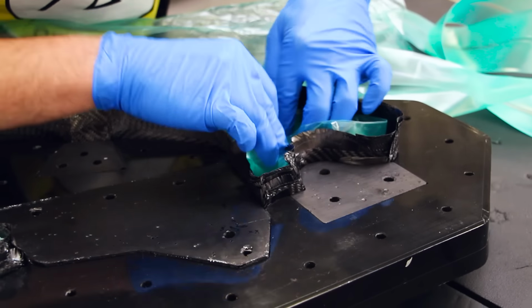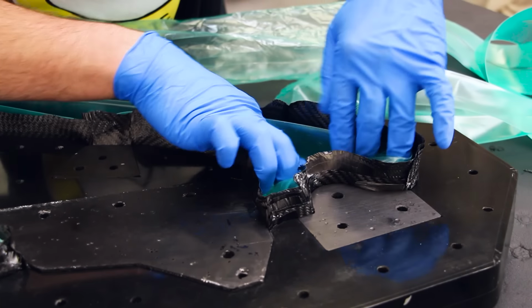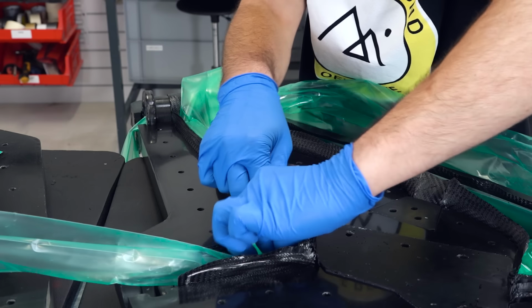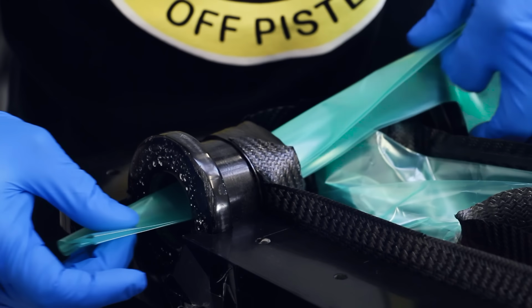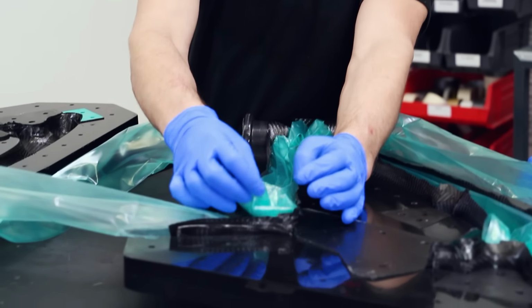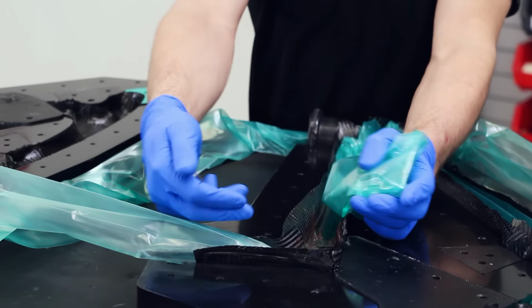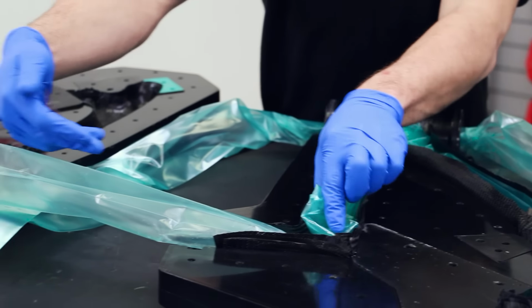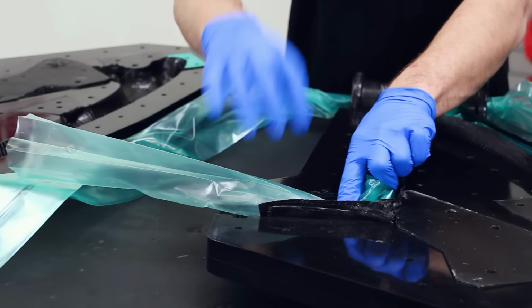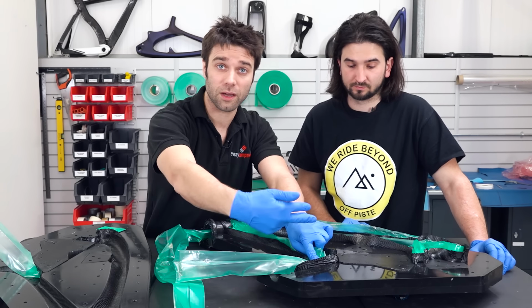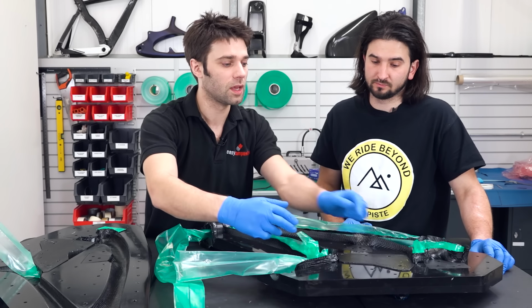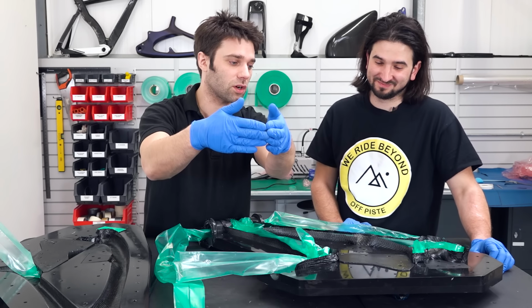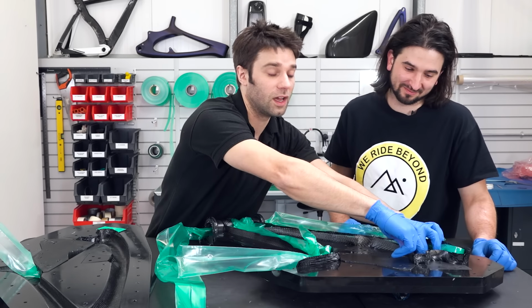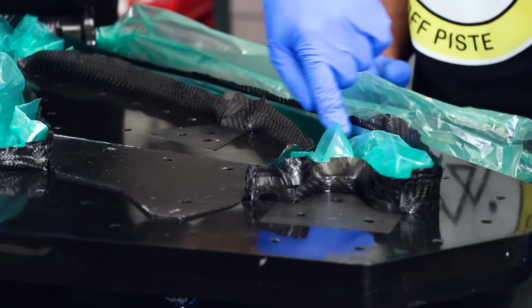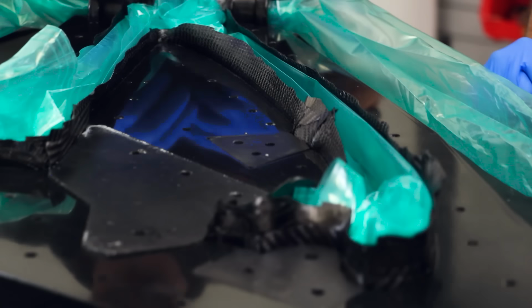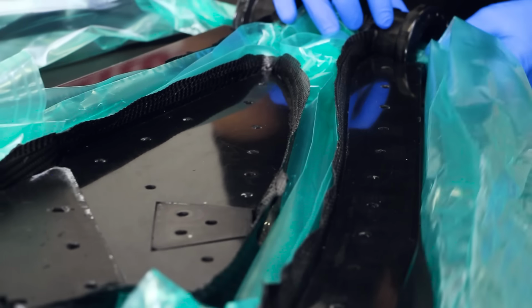This is the 4 bags in the mould. So each one of these is sealed at the end, so it's not a continuous tube. We've got one bag that comes in through the head tube, along the top tube, and meets here at the seat tube. And we can see that pairs against the bag that's here. We've got this seat tube bag on this component and on the other side. So we've got 2 bags going in through that same aperture in the seat tube, and then they pair off either side of the shock tunnel, and again they're sealed off at the end here and meet the 4th bag, which is this one on the down tube, which comes out of the bottom of the steerer tube.